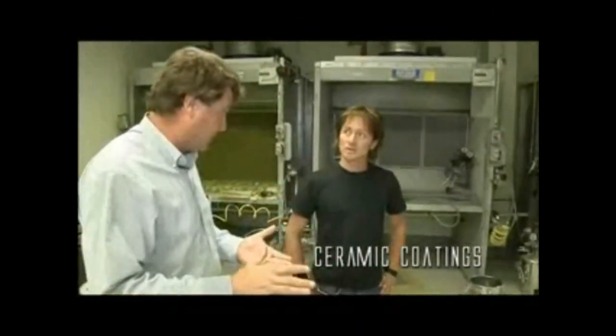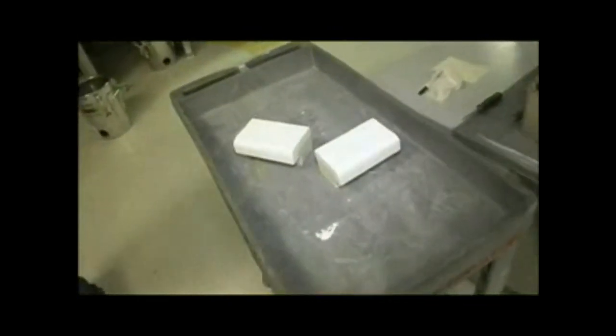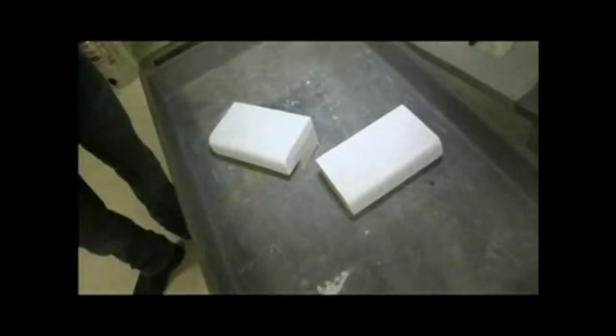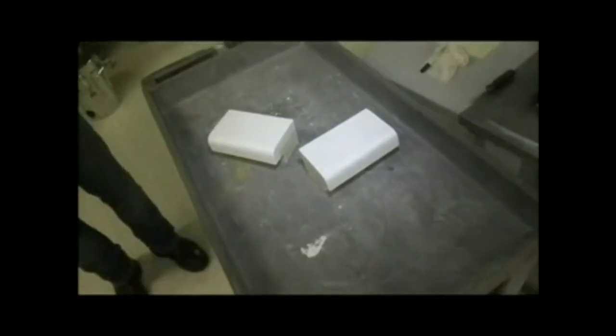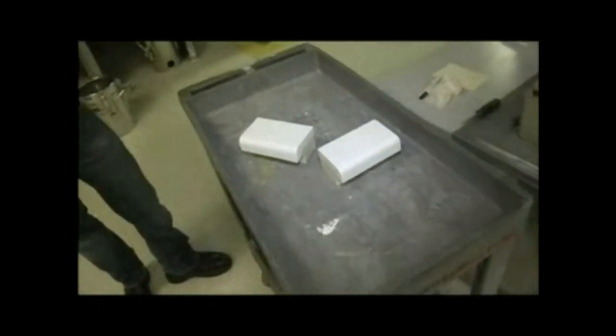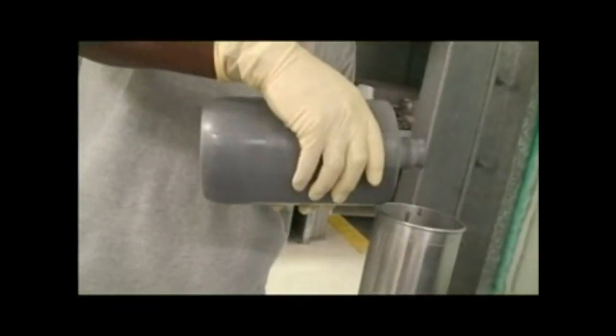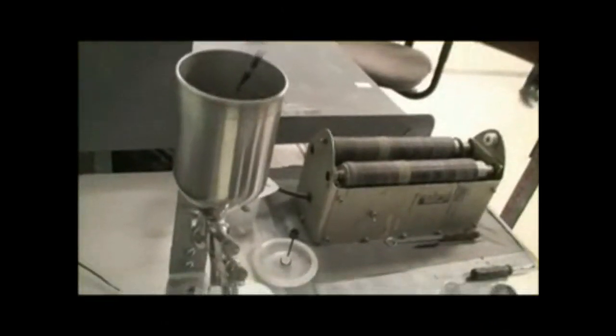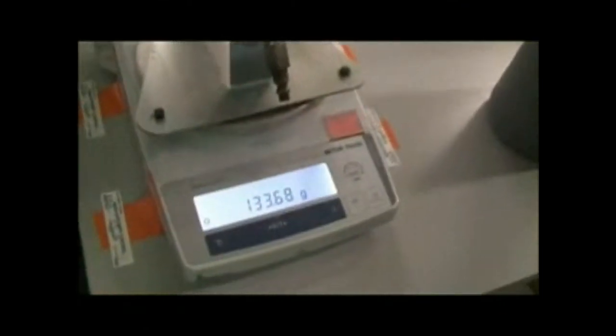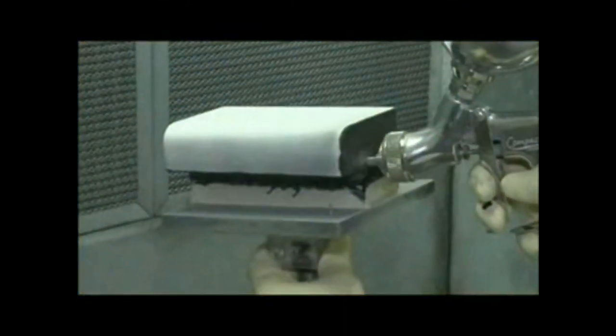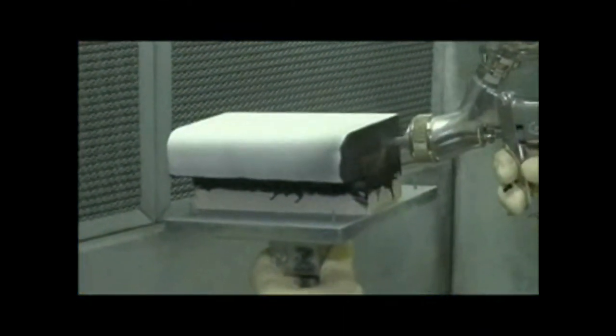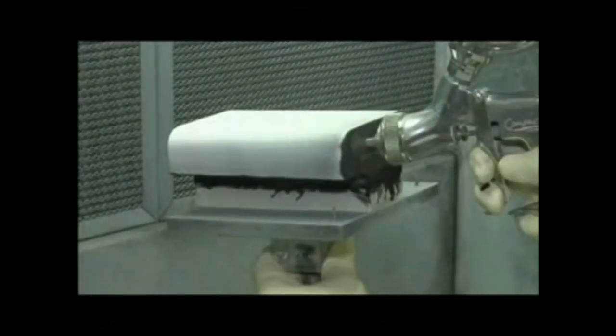The materials themselves, at this point, do not have a lot of strength. So we put a coating on. It's either a black or a white coating, depending on the emittance properties required of the tile. And it's put on in several layers. We make the coatings in here. They're basically very finely divided ceramic powders, either in alcohol or water, with various thickening agents and emittants and pigments. They're all sprayed by hand.